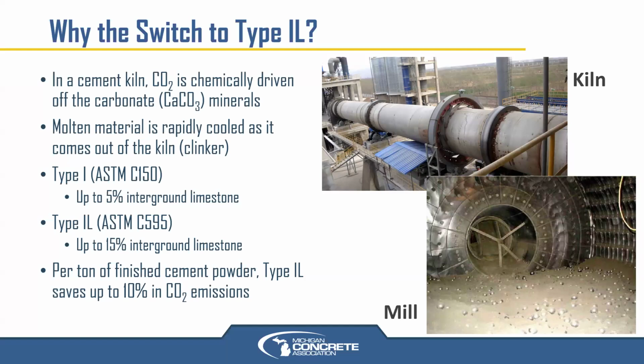The molten material, though, as it's chemically combined into one product, one mineral type of product, is rapidly cooled at the bottom end of that kiln. As it comes out, it's rapidly cooled and actually goes from a liquid back to a solid. And when it hits the ground, it's kind of an aggregate type of particle, and actually makes a clinking sound, which is why the folks that invented this whole process termed it clinker, because that's literally the sound it makes after it's cooled and falls on the ground.